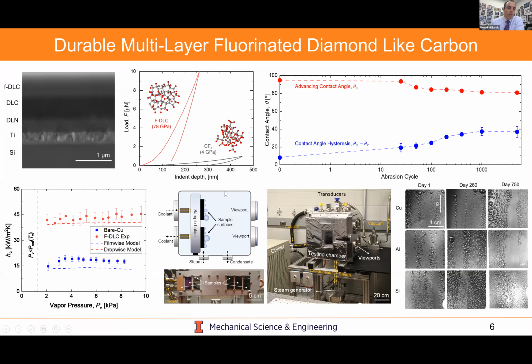And indeed, if you plot the nano indentation curve, the load as a function of indentation depth, you see that for FDLC coatings, your Young's modulus has inorganic-like behavior. So it's much stronger than a typical CFX amorphous fluoropolymer. And if you then do tests of abrasion and plot the contact angle as a function of abrasion cycle, you clearly see much greater durability when compared to state-of-the-art nano-engineered surfaces. In this case, we could go all the way up to 5,000 abrasion cycles using a diamond tip while still maintaining dropwise condensation. We then characterize the heat transfer performance, and by developing systematic experiments that could be run for a long time, we're excited to say that we've been able to demonstrate these coatings on a variety of different substrates for timescales on the order of 3 years at this point.